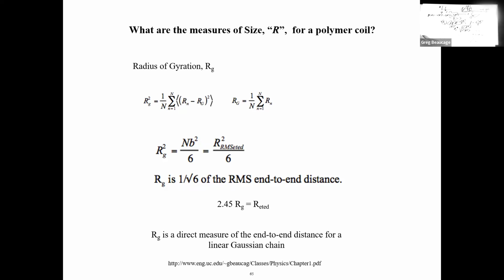So that's important to know about RG, and the way people, like you'll see in papers, use RG for a polydisperse system and they're just using RG as the size, as the radius. It's not the radius, and it's not really going to reflect the size. It's like a beach with sand on it and a couple of boulders: it reflects the size of the boulders, if you're measuring all the particle sizes in it. So it's a useless number, essentially, unless you're interested in boulders.